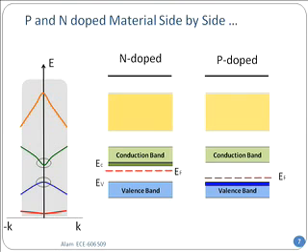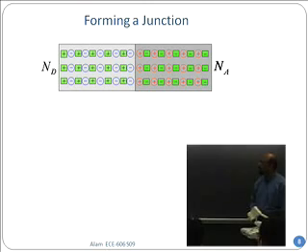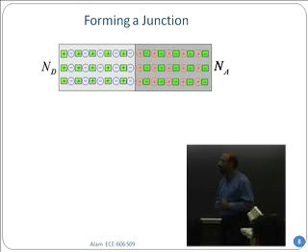Rather, you need to diffuse things in so the junction doesn't have too many defects. That's what we did, right? Diffuse atoms in, and therefore the junction doesn't have too many defects. Only then will interesting things happen, as we'll see. Assume, therefore, that this is a diffuse junction. The junction has been created and there are no surface defects. Then in that case, what will happen?